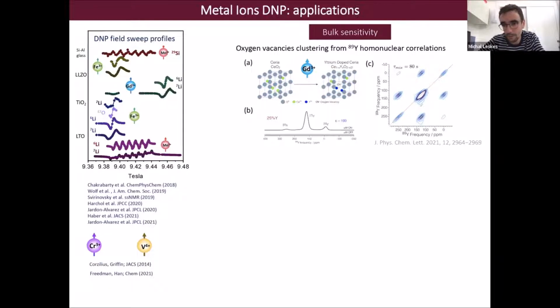And with that, we were able to obtain DNP enhancement of the yttrium-89 NMR signal, with a signal enhancement of a factor of almost 200. And this gain in sensitivity allowed us to do two-dimensional yttrium-yttrium correlation spectra, which is extremely challenging due to the very low gyromagnetic ratio of yttrium. And once we had these two-dimensional maps, we were actually able to say something about the oxygen vacancy distribution, this structure, which is very relevant for its ionic conductivity properties.